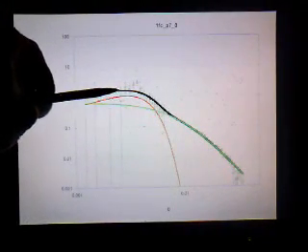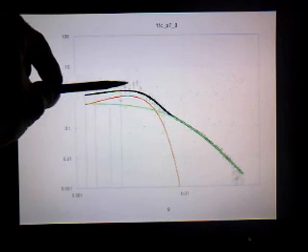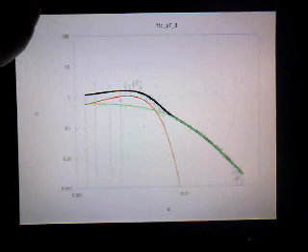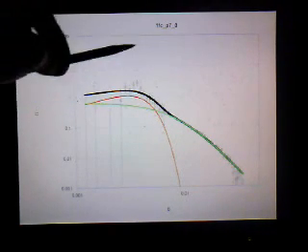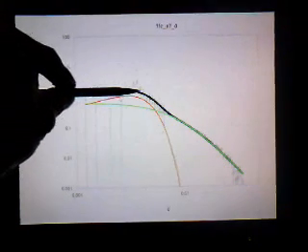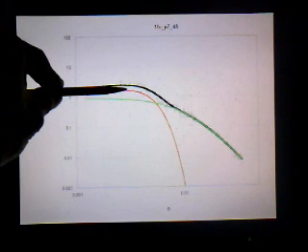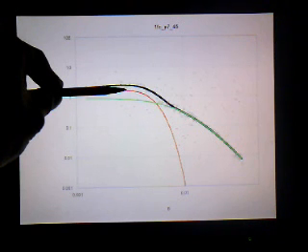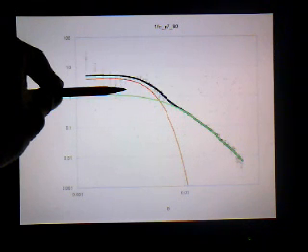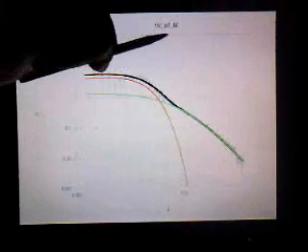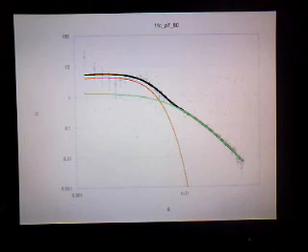Because remember, there is no empty can contribution to these data. So these are data taken. These constitute SANS signal from our sample, which includes both the thin film and the substrate. And this is a nearly saturated, we would have thought a nearly saturated condition. And you see the signal is quite low. It increases somewhat as Q deviates from the direction of the applied field. Increases more. Notice that we always see the spike only when we have a condition of Q perpendicular to applied